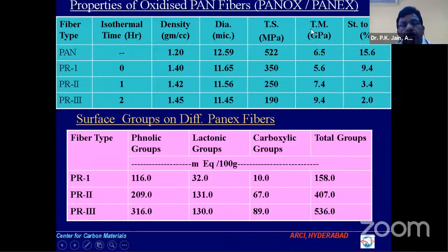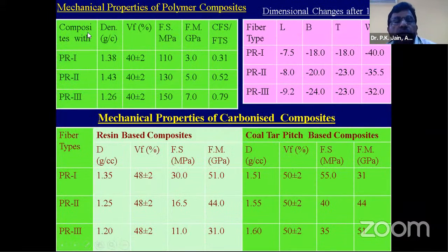These are the properties. If you see the surface energetics of these, the highest surface energy was in PR3 as compared to PR1. So when we made the composites with a fiber volume fraction of 40 plus minus 2, and then the flexural strength we found, PR3, having the highest surface energetics, is giving a high strength. And of course dimensional changes are also high when you take the higher surface energetics. But this is a resin based composite and the coal tar pitch based composite. So these are the two different composites.